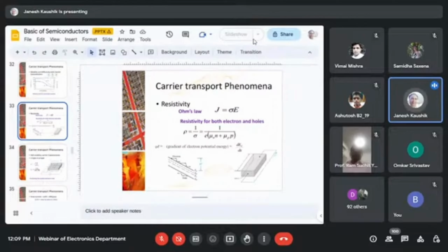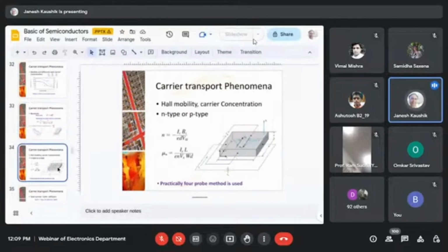When we do this experiment, we can calculate the resistivity of that material, and we use this to calculate the mobility from the Hall measurement system. This mobility we get from this electrical measurement system, that is Hall. In addition to measuring the resistivity or conductivity by applying an electric field and measuring the current, we put this bar in a magnetic field, and due to the deflection of electrons and holes in one direction, we get a Hall voltage on different faces, and we measure that. That gives the polarity, meaning N type or P type, and gives us directly how much is the concentration of doping in that particular layer.